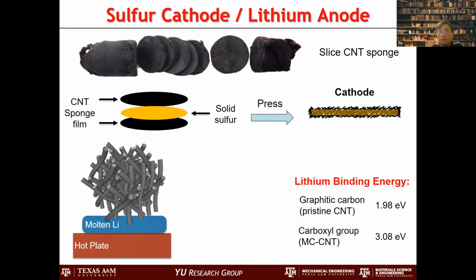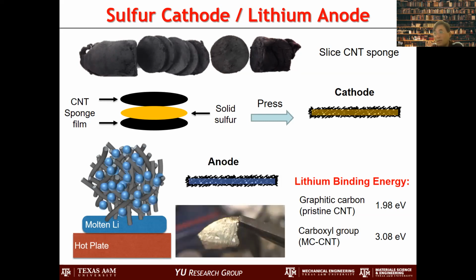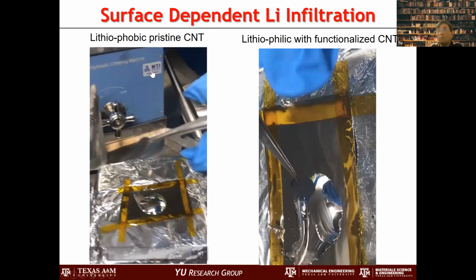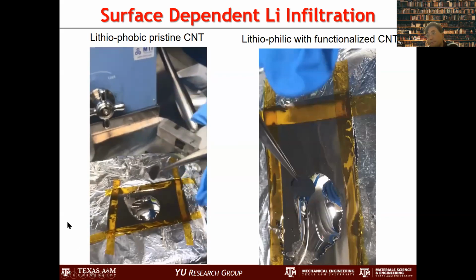For anode is tricky, and we want to actually infiltrate the lithium inside. But it turns out, initially this was not that easy. So I'll show you the video. And so this is a basically pristine carbon nanotube. And you see that the pristine carbon nanotube here. And this is a molten lithium. So we actually increase the temperature here, make it liquid phase lithium inside the glove box. And you can see that.